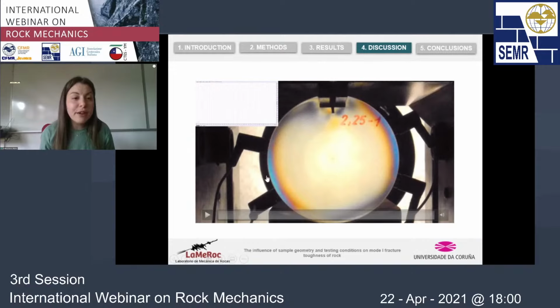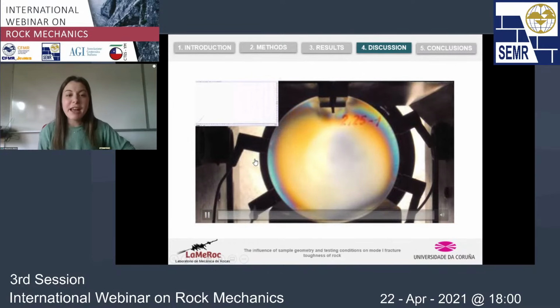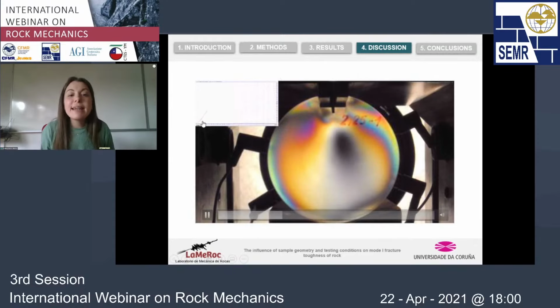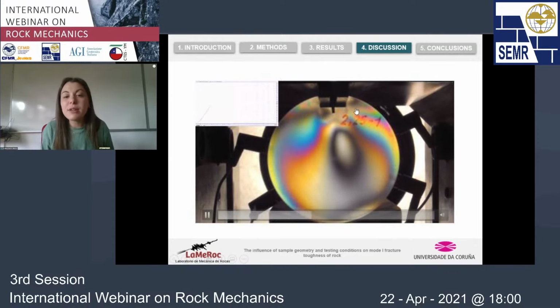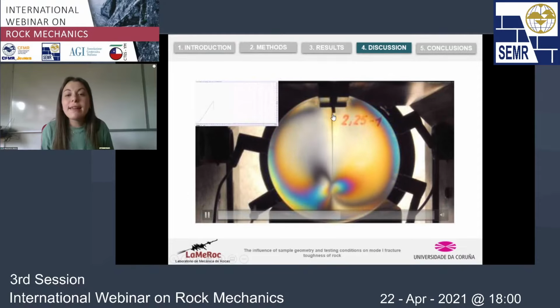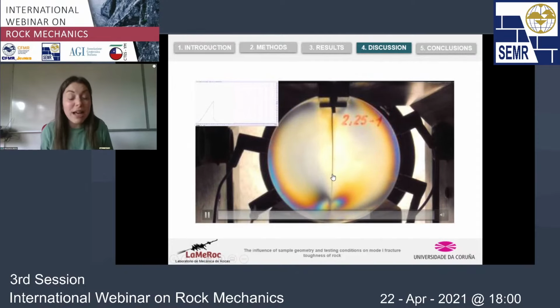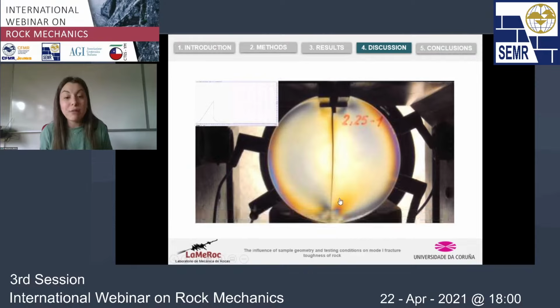I have a video here. You are going to see here on this corner of the slide how the loading curve, how the load increases. And here on the sample, what we are going to see is a color pattern. Each color that we are going to see on the sample is reflecting a different level of stress. The speed of the video is like 16 times higher than it should be. But we see that the load increases, that the stress is concentrated here on the contact with the jaws and the notch tip, and that at some point the fracture propagates, that we have a very good control on this fracture propagation, and that this stress is concentrated here at the level of the notch tip, of the crack tip, and is released here on both sides of the sample.